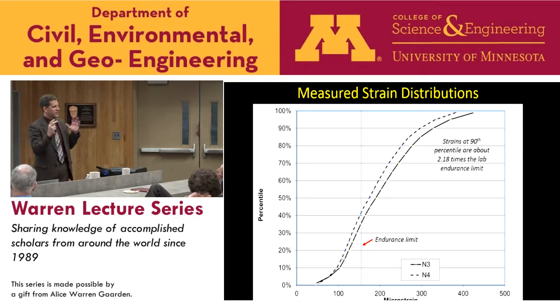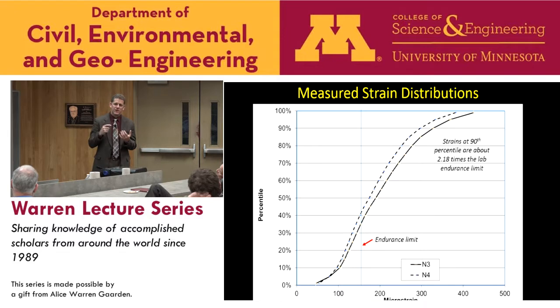In the field, we have temperature cycling, we have rest periods between trucks, wheel wander. In the laboratory, it's a beam of asphalt, and it's flexing at a constant temperature and no rest periods, that kind of thing. What this tells us is that if we design for 150 microstrain, it's going to give us a conservative design, because clearly we can sustain much higher strains and not have that bottom-up fatigue cracking.